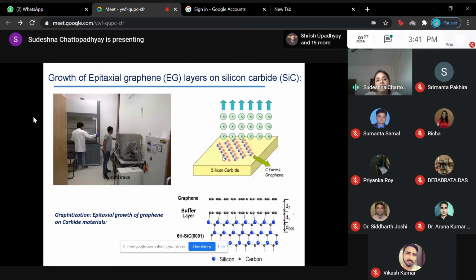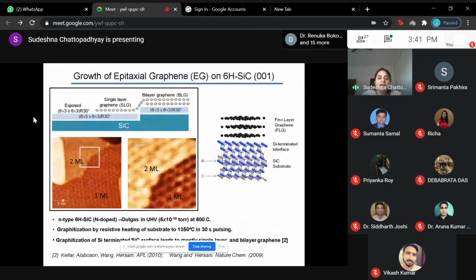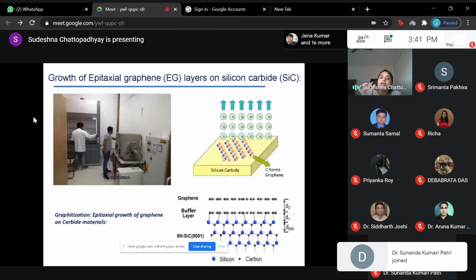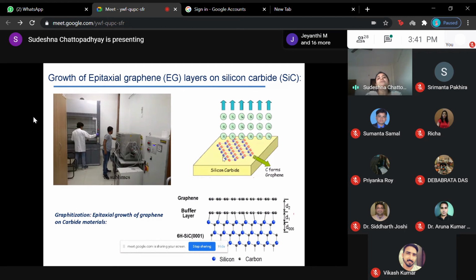As I have told, we have developed this process here, but we also used low temperature graphitization in my previous work at Northeastern University in the US. There I used both ultra high vacuum as well as ambient conditions, to see the changes and differences. For ultra high vacuum, the graphene layers are of very good quality, but the problem is you cannot put a bigger sample in the system. Ultra high vacuum means around 10 to the power minus 10 torr, so your chamber will be very small, otherwise it is very difficult to maintain that pressure. That is why you are restricted in sample size.